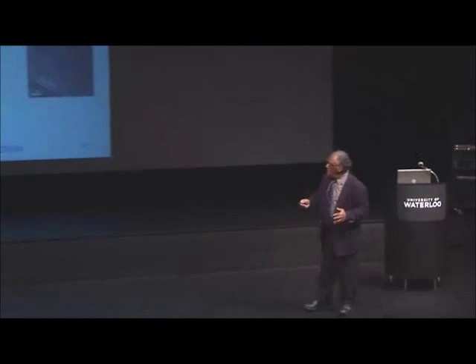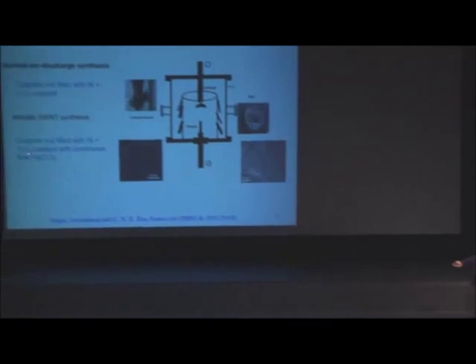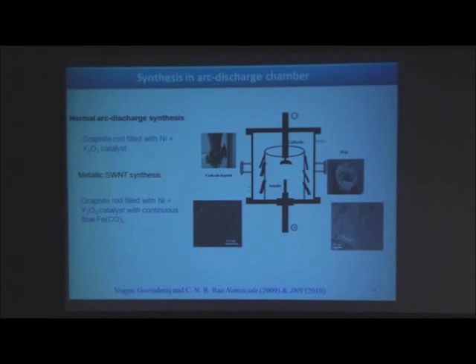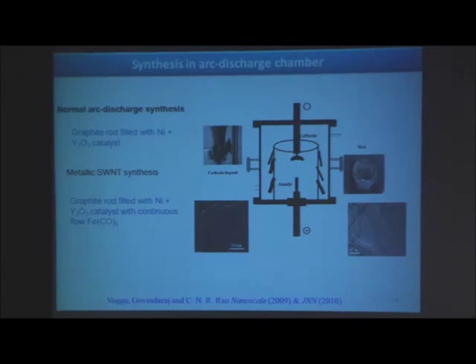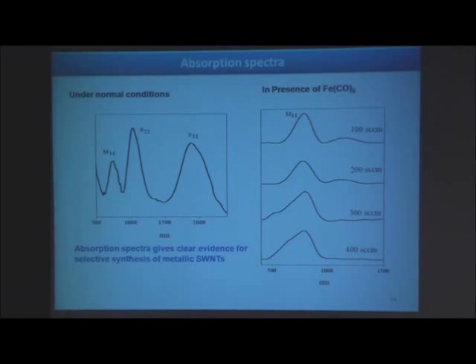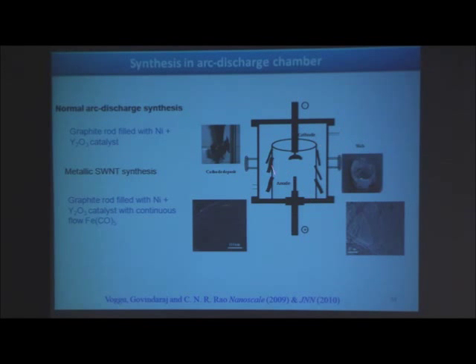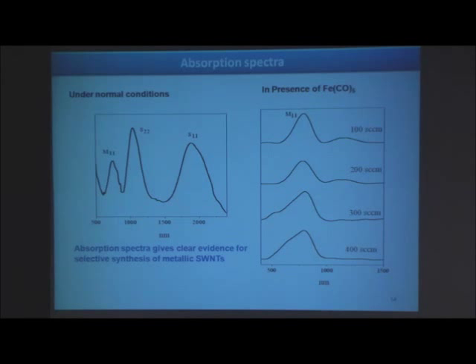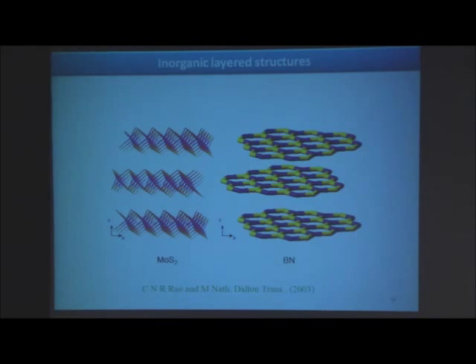But here, one of my students actually was doing arc discharge to make single-wall nanotubes. He just put iron pentacarbonyl in the gas phase, just like that, along with the gas discharge. And what he got was all the nanotubes we picked on the surface of this chamber were only metallic. You see, only metallic nanotubes in one-step synthesis. So this is another thing. You can see the mixture would be like that: 3 transitions, 1 metallic, 2 semi. This is the only metallic transition in the presence of iron pentacarbonyl.